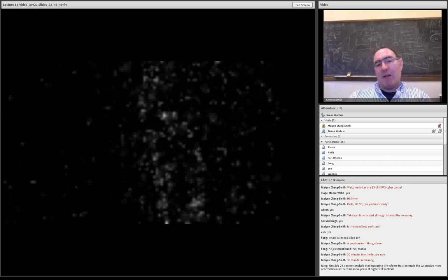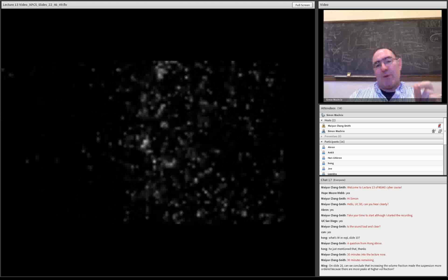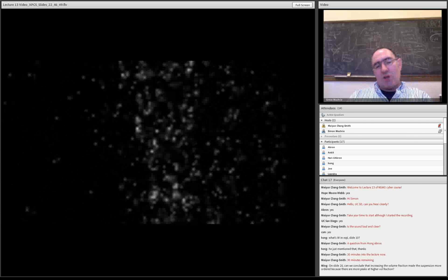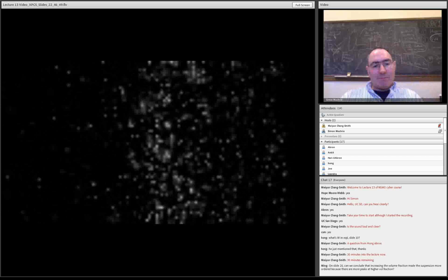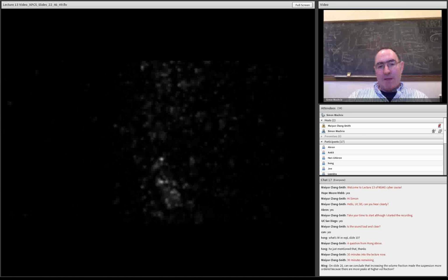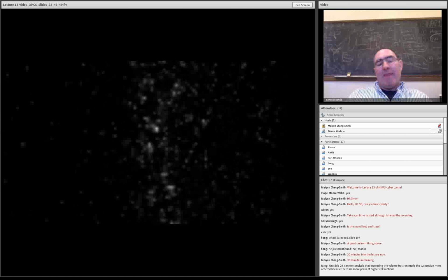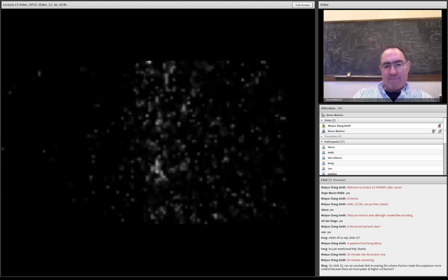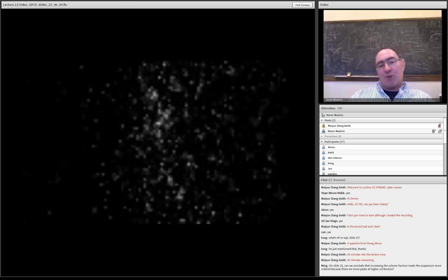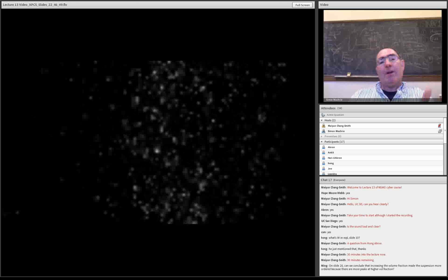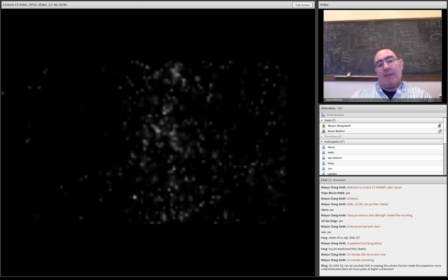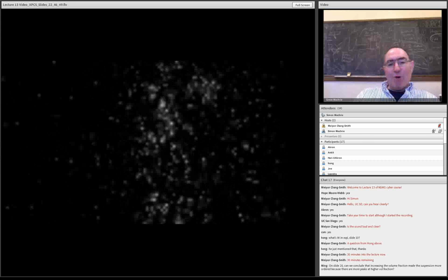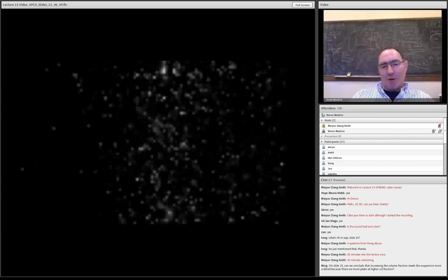So we take a pixel, we measure its intensity as a function of time, we autocorrelate that intensity as a function of time for that pixel, and then we add to that all of the other pixels at the same wave vector, and in this way we build up the wave vector dependent intensity autocorrelation function. So I think we can stop the movie now, and I'll show you what those autocorrelation functions look like.